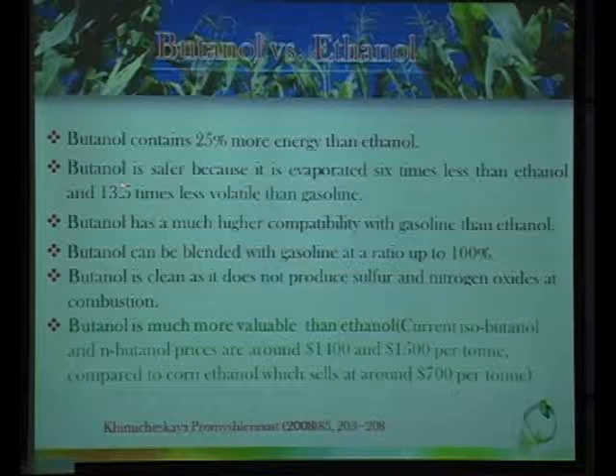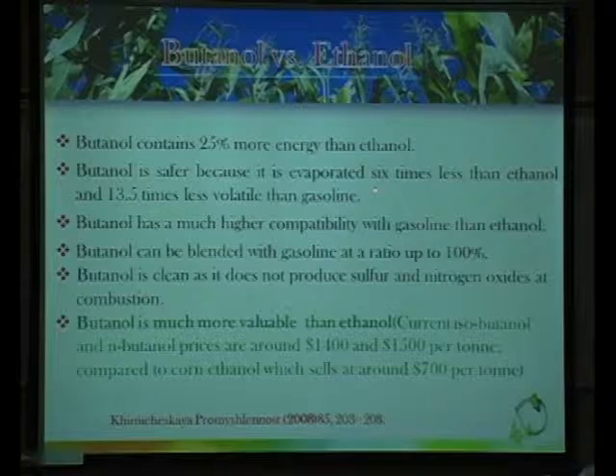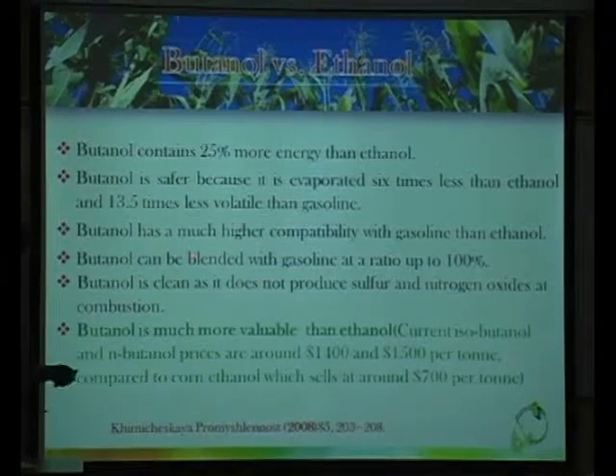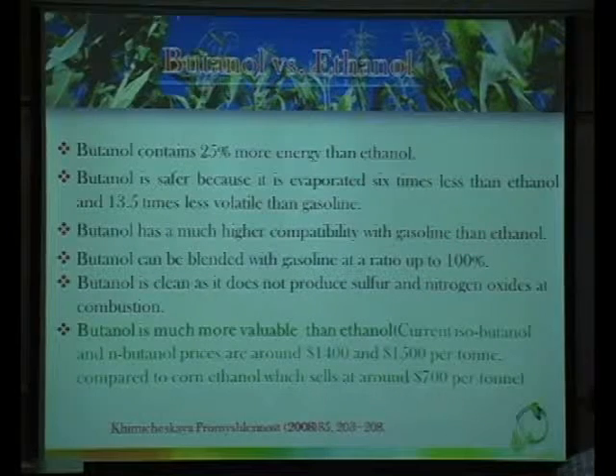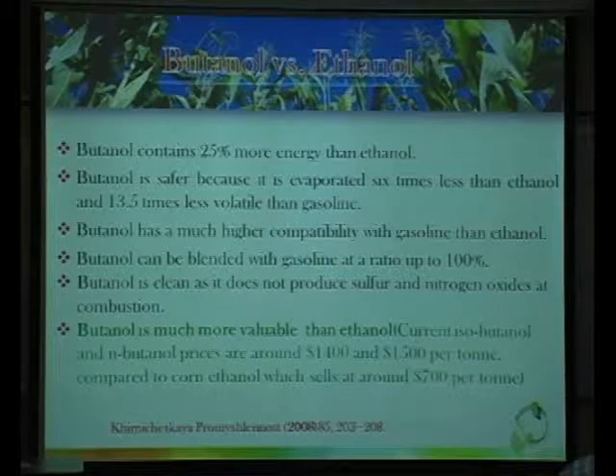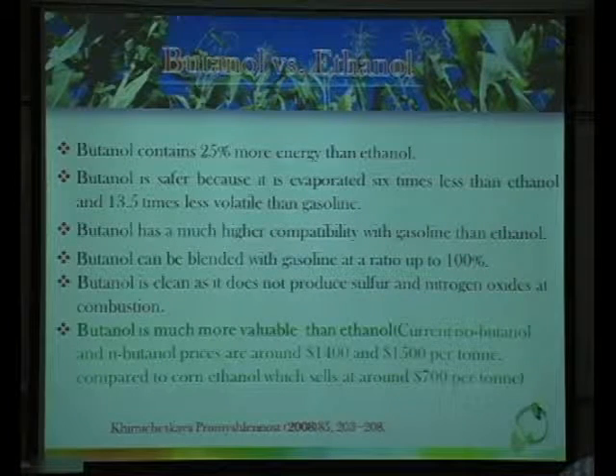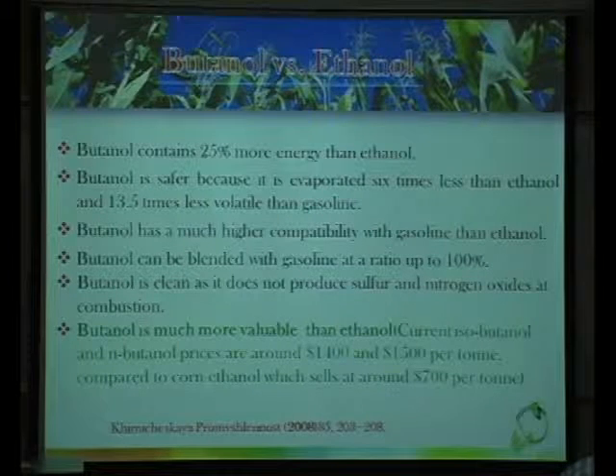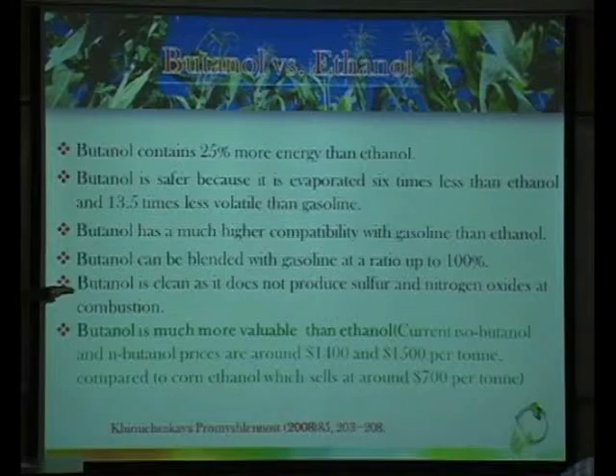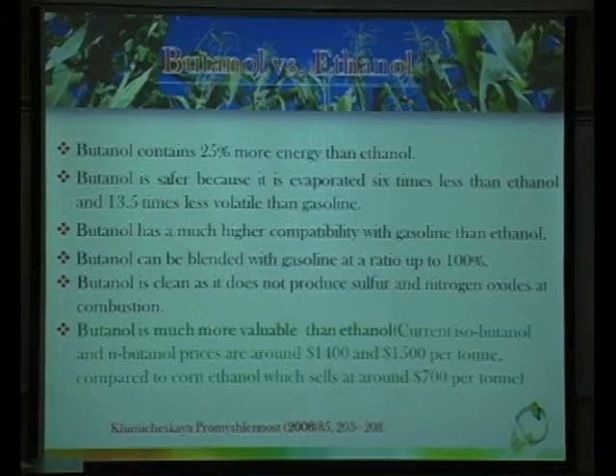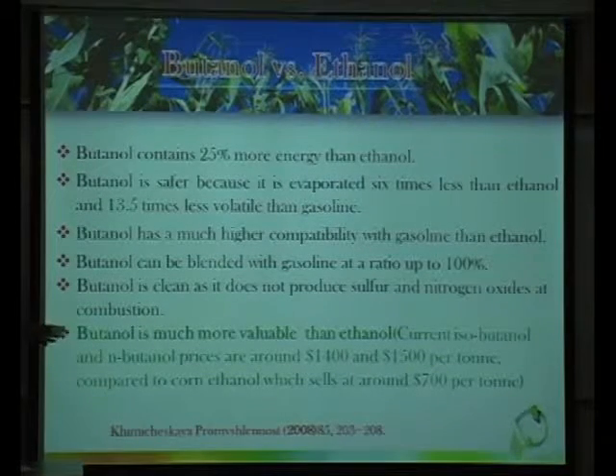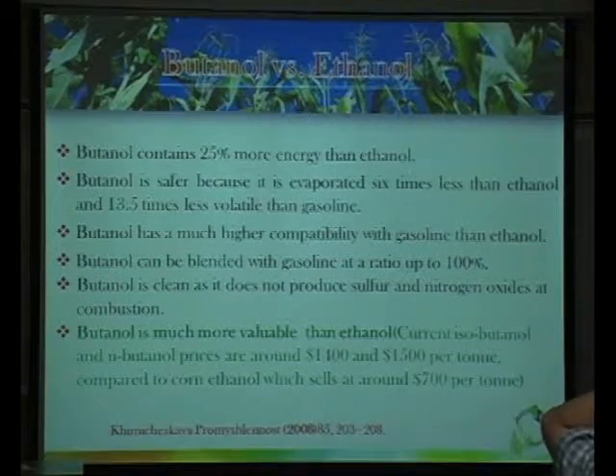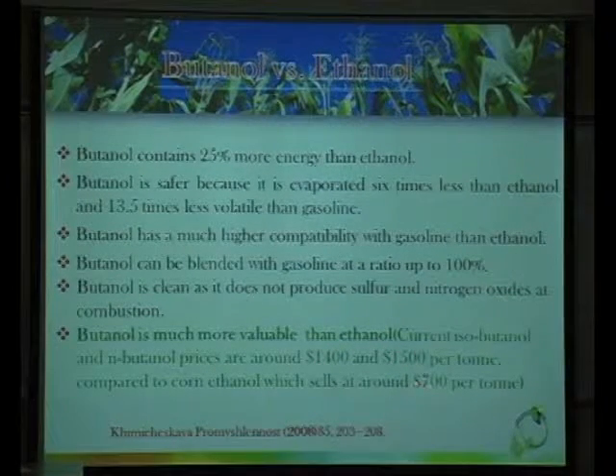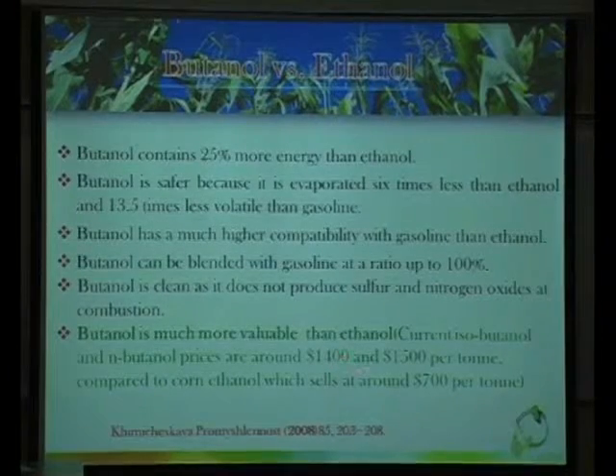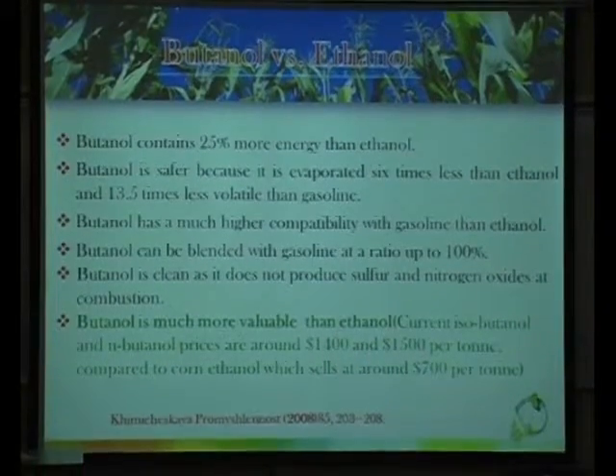Okay, butanol versus ethanol, we already know some of this. Butanol has a higher heating value. Butanol is safer because of its vapor pressure. Butanol has much better compatibility with gasoline and can be blended with gasoline easily, up to 100%. Unlike ethanol, if you blend too much, you get two-phase separation because it's not soluble in gasoline. Butanol is different. And butanol is clean because it does not contain any sulfur or nitrogen, which makes it a clean fuel. Butanol is also much more valuable than ethanol. Looking at price only, ethanol is about 700, but butanol is double, 1400 or 1500. That's the economic value of butanol. It's more expensive.